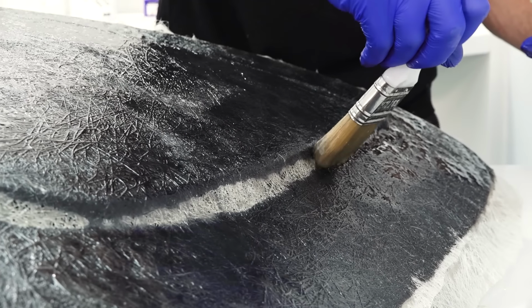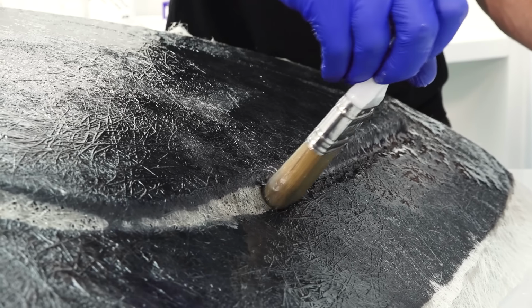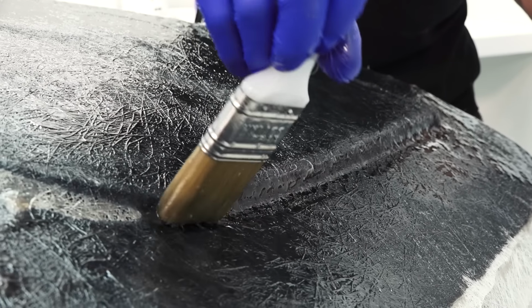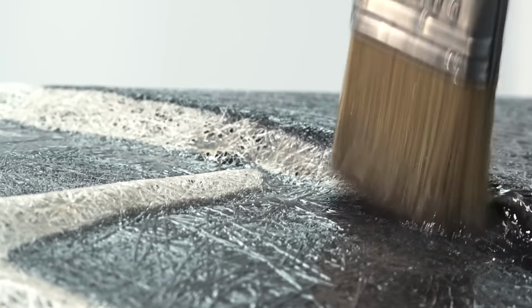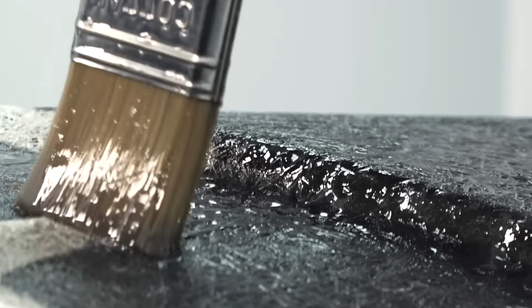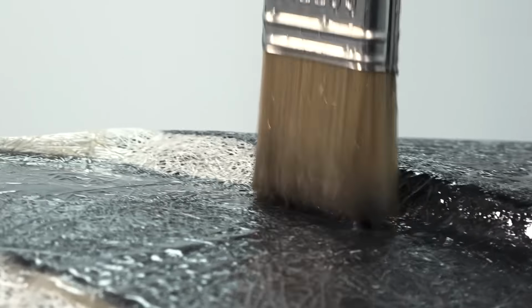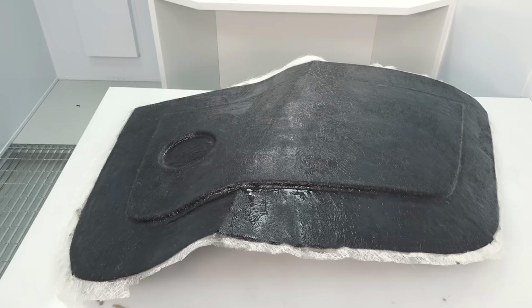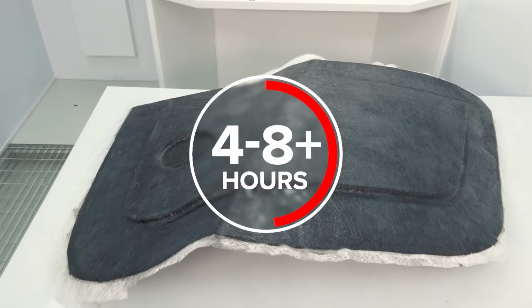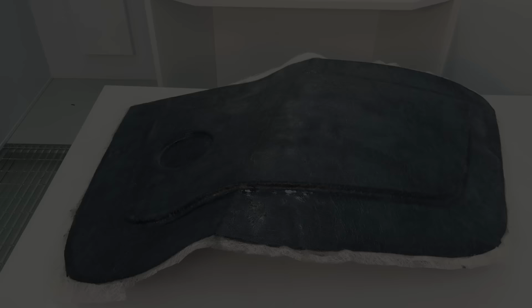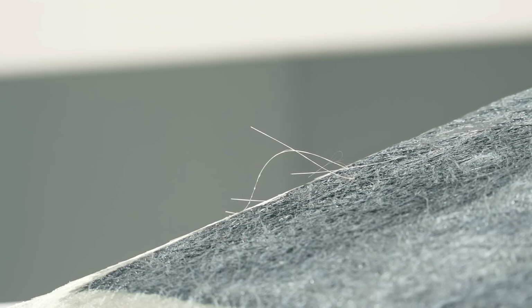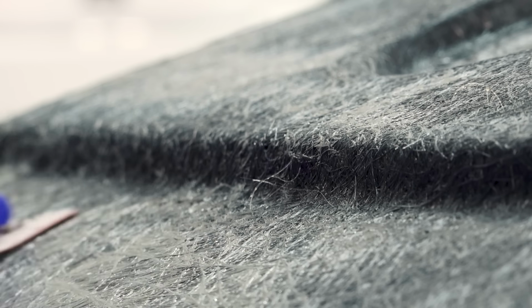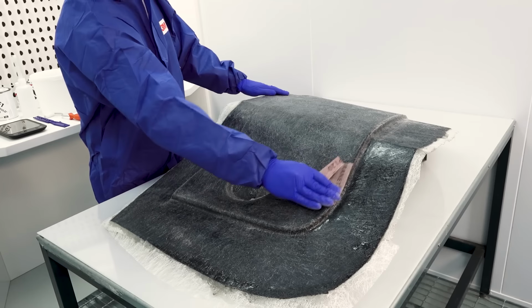Do pay particular attention in the corners where air will often become trapped. If you find there are any air pockets, they should be stippled out with a well-saturated brush. Once you're completely happy that the matting is fully wetted out with no air pockets or voids, then it should be left for 4 to 8 hours to cure. After curing, inspect your mould for any coarse nibs or splinters, which should be knocked down with a coarse sandpaper so that they won't interfere with the next layers.